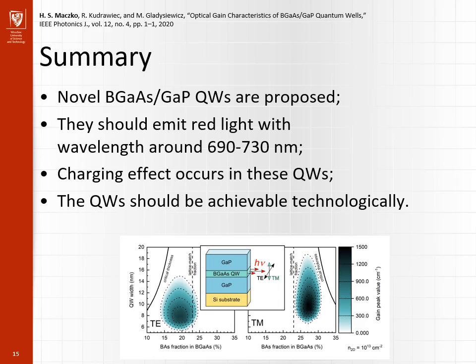It should emit light with wavelength around 690–730 nanometers. Because of delta valleys, a thin layer should charge positively in reference to the barriers. Theoretically, these structures should be possible to manufacture.